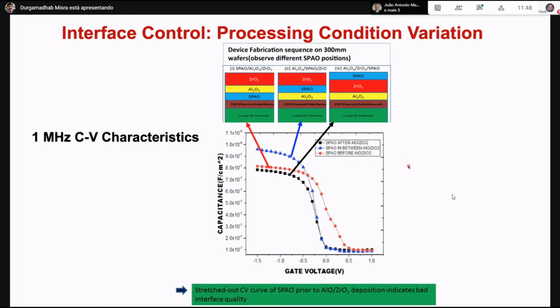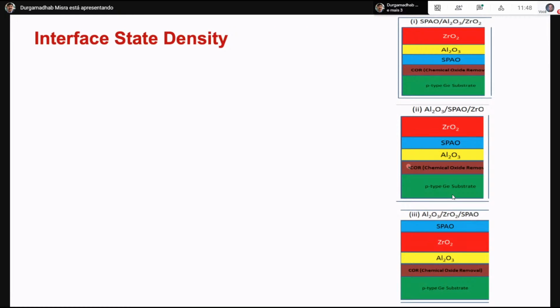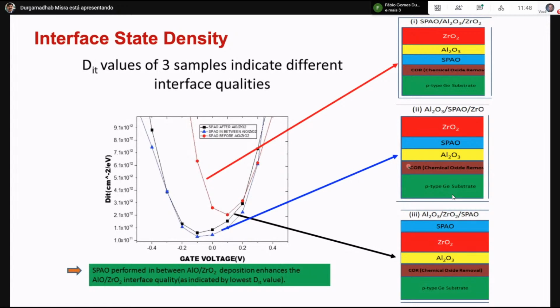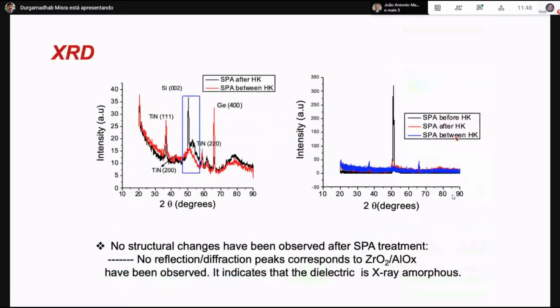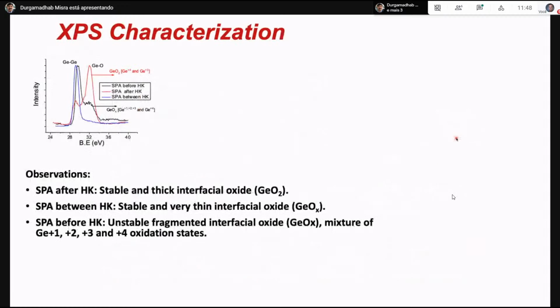And that gave some idea, so now let's look at the device to understand why this improvement took place. We also looked at the interface density, which also came down, and it was the best for the one in the middle. Then we looked at the crystallinity of this film. In the XRD, we found all these films were still amorphous, so we have nothing to worry about. Then we looked at the XPS characterization to see what exactly is going on.